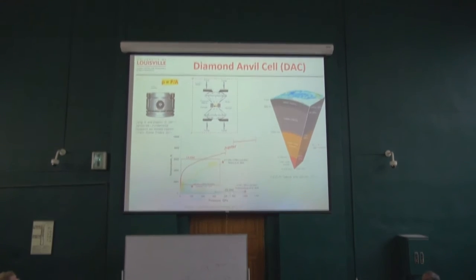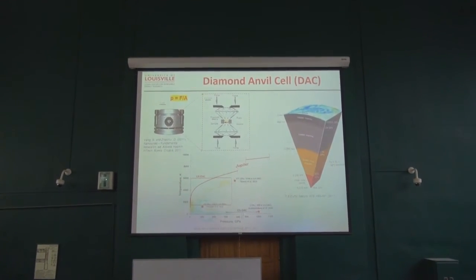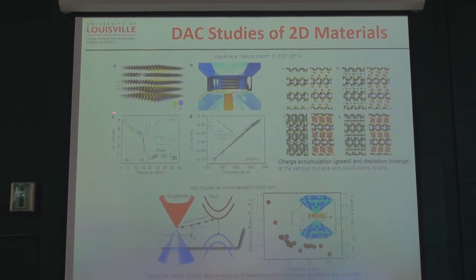People have done this high pressure work for other 2D materials. Let me quickly show you. These are some of the works other people have shown, for example molybdenum disulfide. At ambient temperature and ambient pressure, it is more like a semiconductor, so you have this linear temperature coefficient, but when you go to about 15 gigapascal, it immediately changes phase and becomes a metal. You can show going from a semiconductor to a metal phase transition under high pressure. People have done this for other 2D materials.